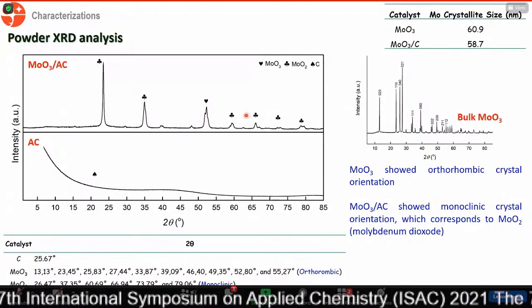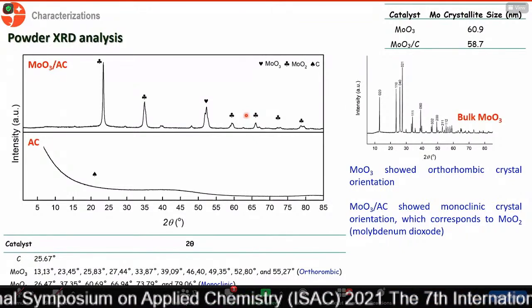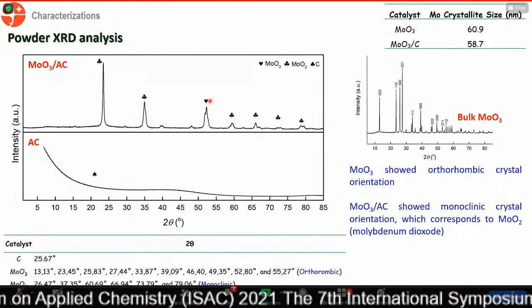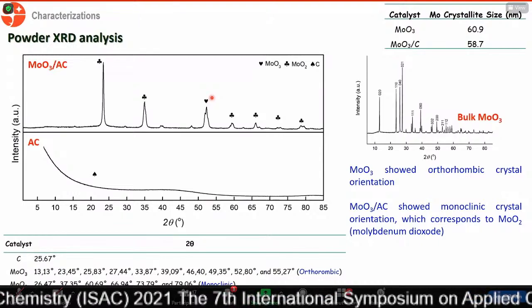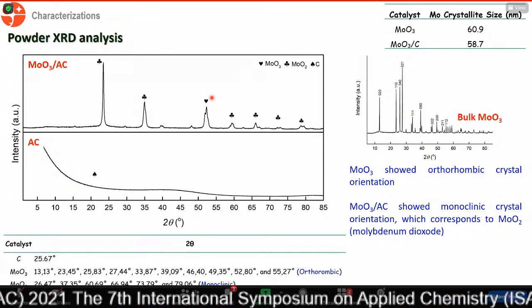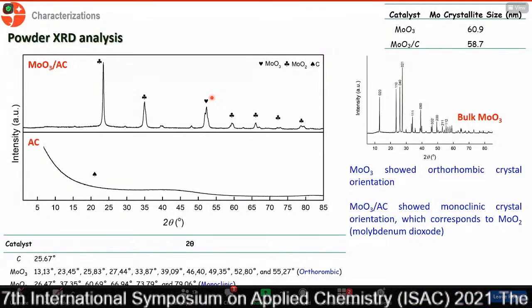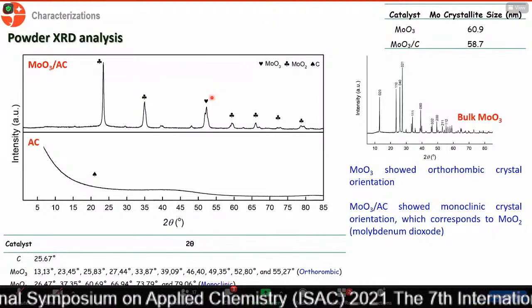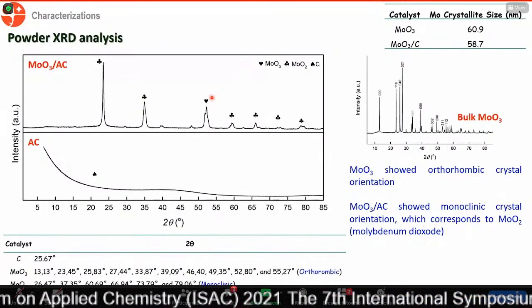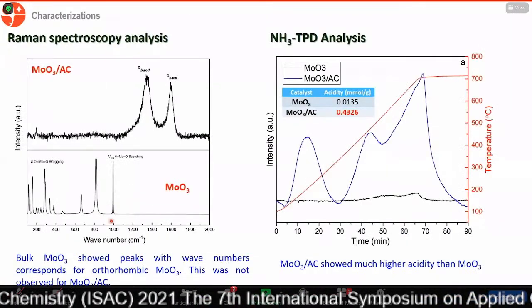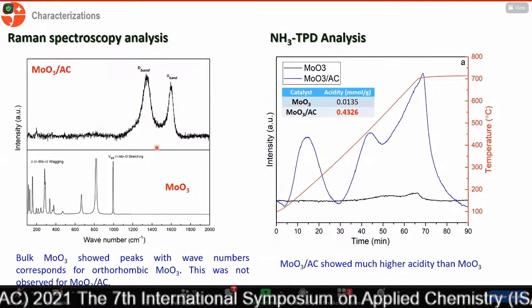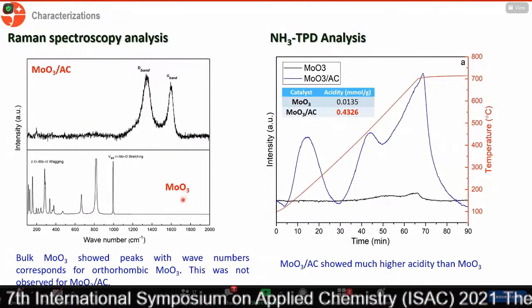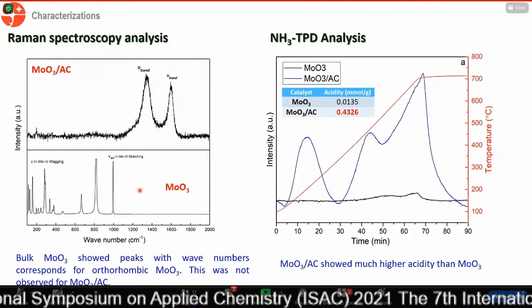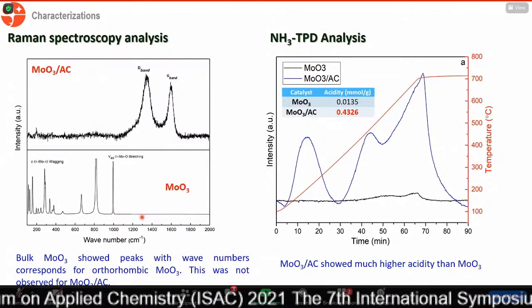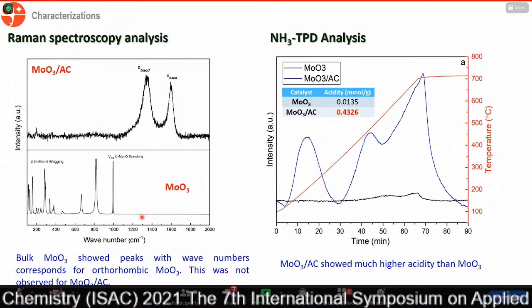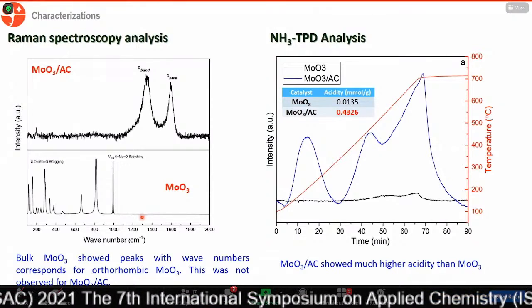However, our synthesized catalyst, which is molybdenum oxide on activated carbon, showed a monoclinic crystal, which corresponded to molybdenum dioxide. This molybdenum dioxide is an intermediate product of the conversion of molybdenum trioxide into molybdenum carbide. However, it is formed due to the insufficient temperature of carbon diffusion to convert the oxide phase of molybdenum dioxide to molybdenum carbide. From Raman spectroscopy analysis, we can see here that the bulk molybdenum oxide shows several peaks with wave numbers corresponding to orthorhombic molybdenum oxide. However, this was not observed for molybdenum oxide supported on activated carbon.